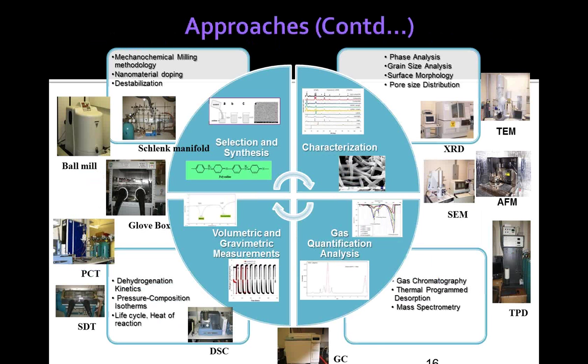So this is again the big chart of what capacity or capability we have for looking at the different systems. On the left hand side is a ball milling instrument for making the hydrogen storage materials with a very high revolution per minute, about 800 revolutions, Schlenk manifold, glove box for preparing these materials, PCT, pressure composition isotherms for measuring hydrogen absorption, desorption, simultaneous differential scanning and thermogravimetric analyzer, DSC, XRD, TEM.